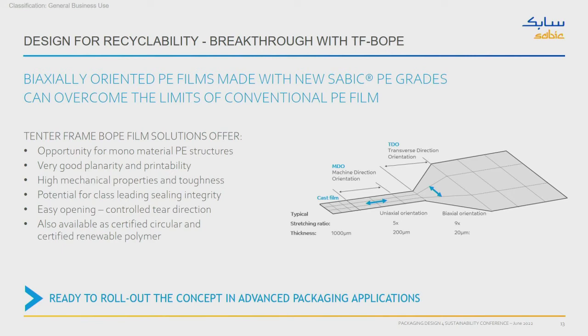Is that something special? I would say yes. It's not that straightforward. Also, Mila talked about the BOPE in the Musepark consortium. We're also part of that in the life cycle assessment, and the BOPE is used in that case. What do you usually do in BOPE? Yeah, you make a cast film. You see it's a relatively thick cast film. It's stretched in one direction, machine direction, roughly 5 times, and then in a tenter frame stretched in TD direction, and then you go from, let's say, roughly 1,000 microns to 20 microns.